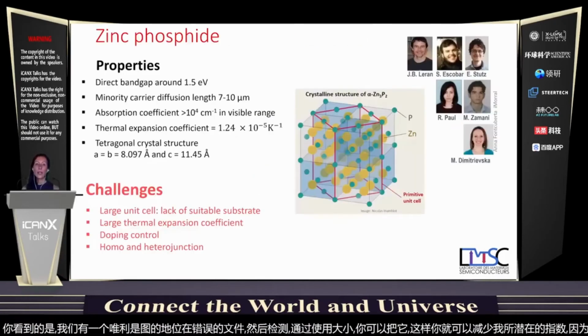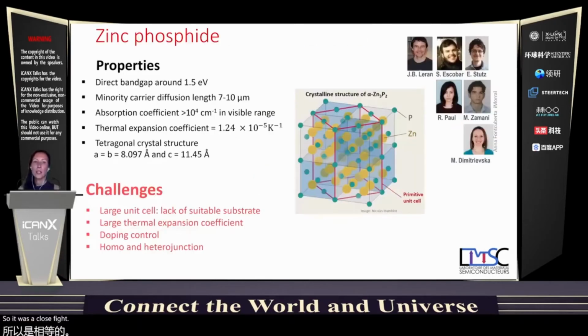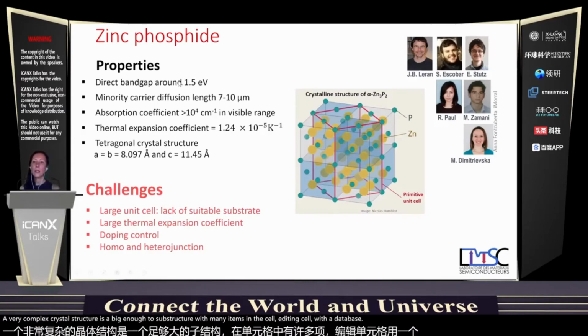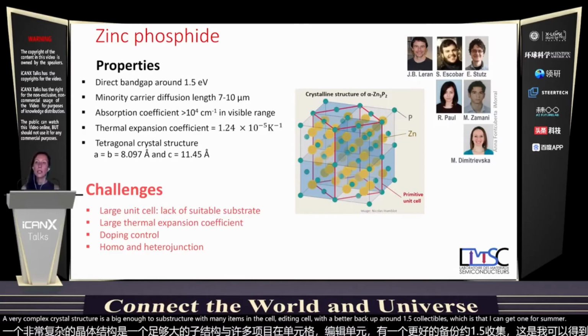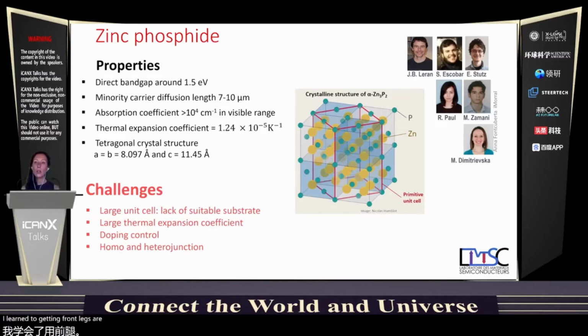So zinc phosphide is a material that has a very complex crystalline structure. It's a tetragonal crystal structure with many atoms in the cell, a very big cell, with a direct band gap around 1.5 electron volts, which is the right band gap we want for solar cells. Minority carrier diffusion lengths are long, and the absorption coefficient is very high.